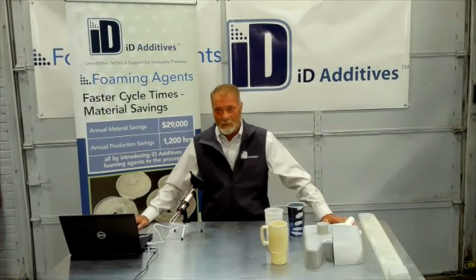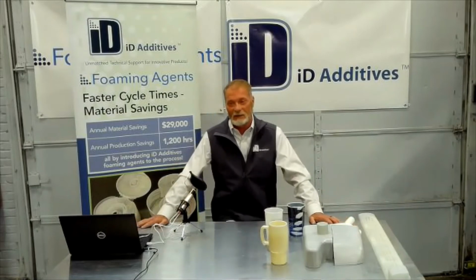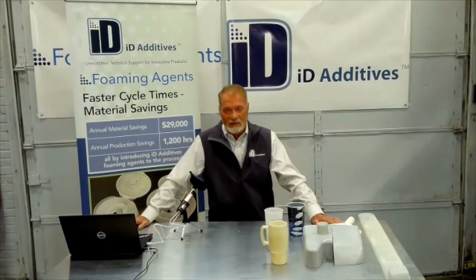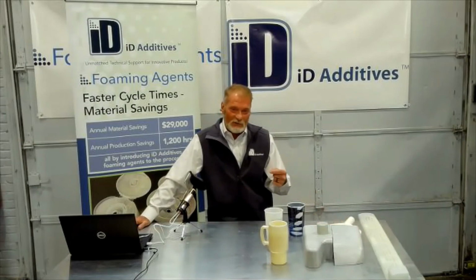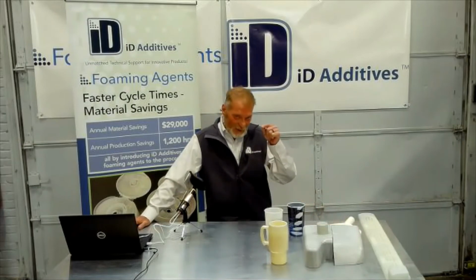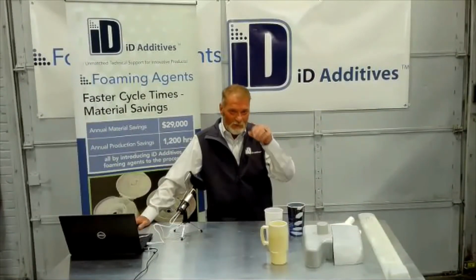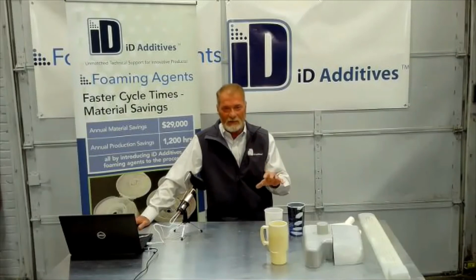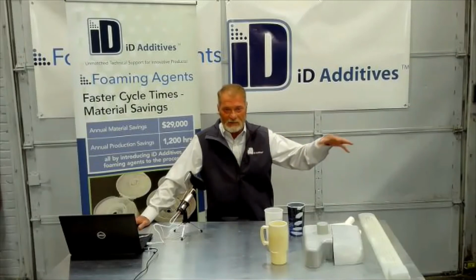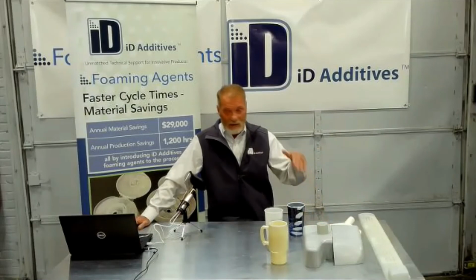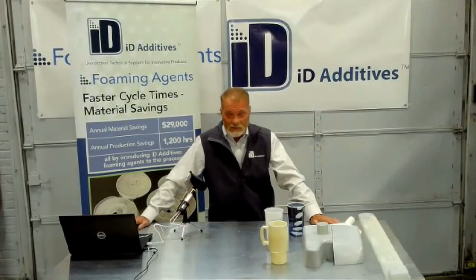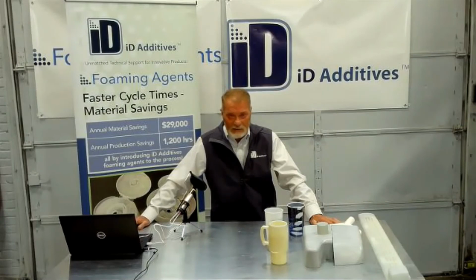Yeah, you can't beat a liquid as far as feeding it in. With pellets, if you're trying to do something like 0.2%, the pellet has to be perfect. Because if you get 2 or 3 pellets and it doesn't drop in perfectly, you're going to get some inconsistencies. But with liquid, you line it out and it just runs so good. So if you're doing profile extrusion, I would highly recommend a liquid azo. Yes, liquid foaming.